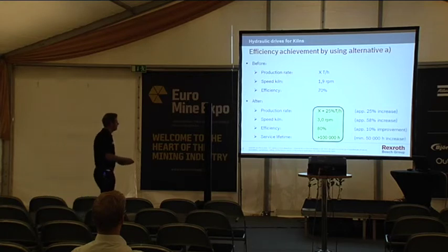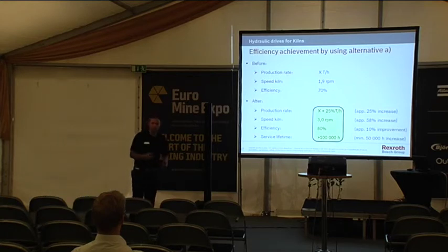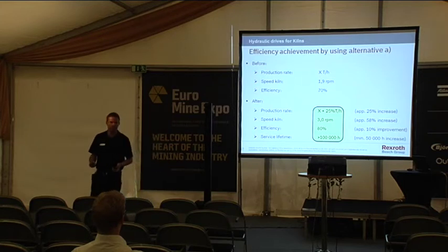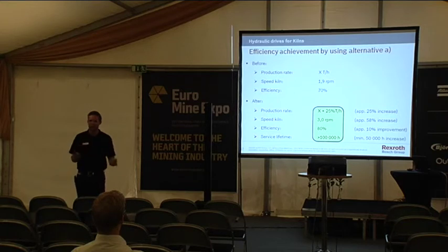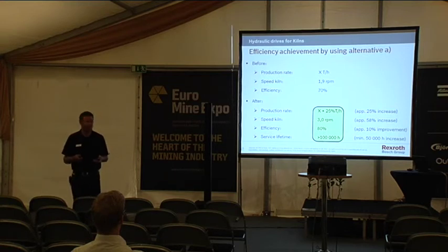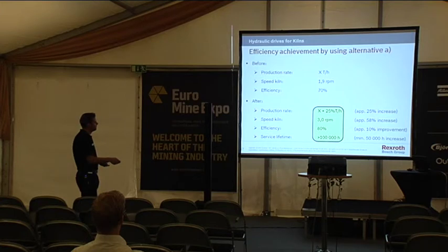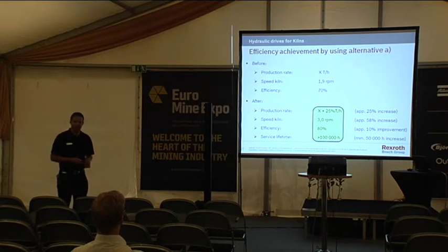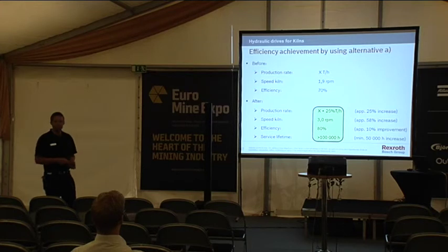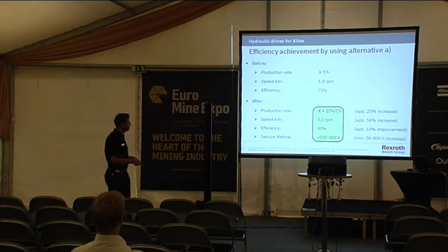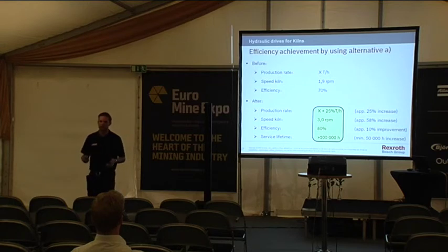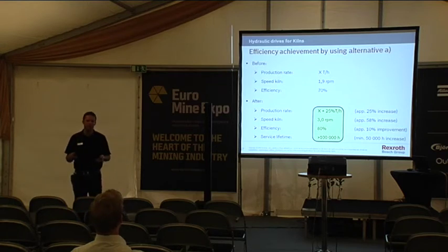But the important is that they increased the production with at least 25%. They haven't tested it to a maximum yet because all the other equipment, like the grate, where they roll the pellets and everything, needs to be upgraded also, so they have higher capacity. The capacity increase in the speed increased by 58%, and the efficiency increased by 10%. That is quite much when you have this kind of high power application. And the lifetime increased by minimum 50,000 hours. That means that they have more than 100,000 hour lifetime now. That's more than 11, 12 years of service life.